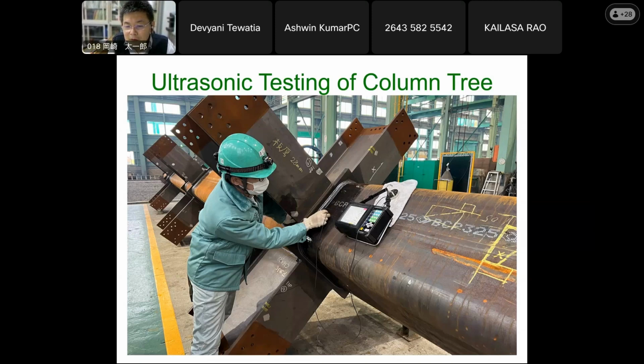Okay, if there is a defect or void, or any defect, that might be inclusion, but any defect will be picked up as a void or a crack or air crack inside the weld. And if the size exceeds a certain size and limit, then the weld must be removed until the defect is found and removed, and subsequently the weld might have to be repaired. Okay, so that's the most important inspection procedure.